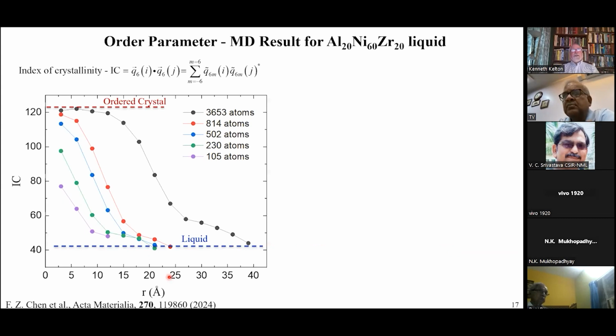Now let's go back and look at the order through the interface. Here, what I've done is show the order parameter as a function of distance. Here is the case for a large cluster. This is a very large cluster that's well past the critical size at the temperatures in this MD simulation. And you can see that at the center, the order parameter is equal to that of the ordered crystal, shown here by the dashed line. And then as you go towards the surface of the cluster, it decays and eventually becomes the order parameter of the liquid. That's what I showed you before schematically or pictorially.